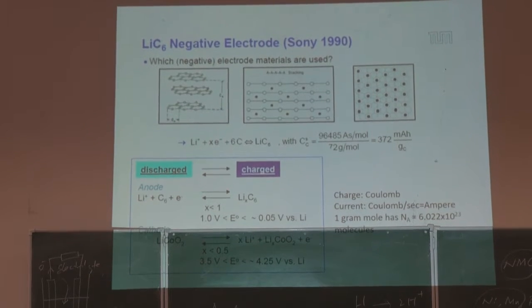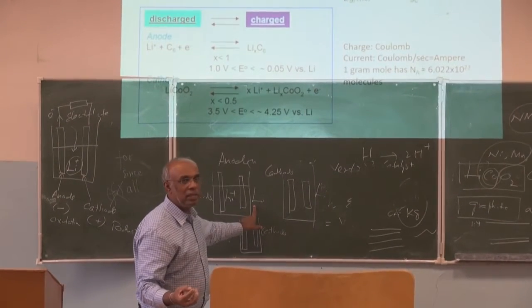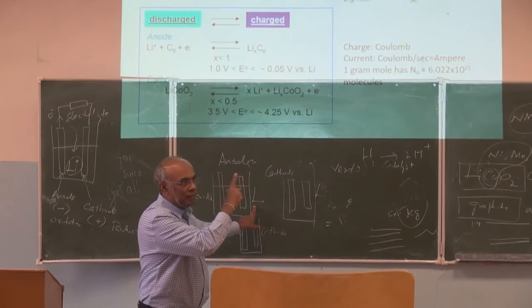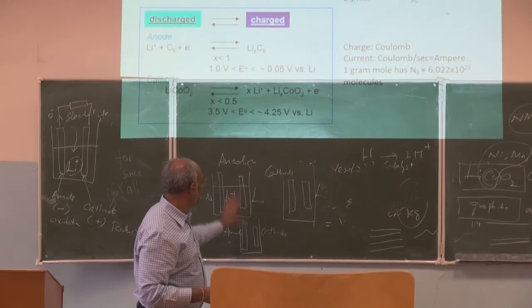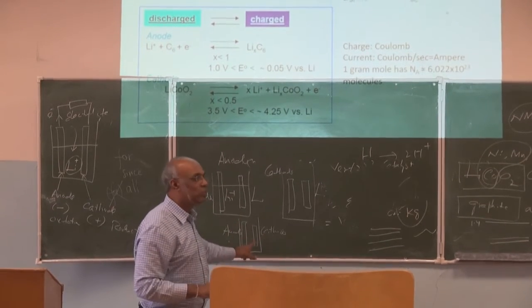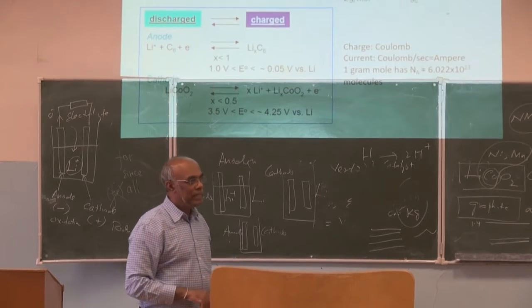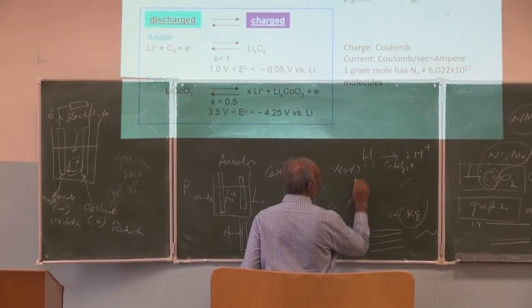So that's why one electrode here is fine. We have lithium, an infinite supply of lithium. But when you put the two materials together, that's the real battery, this one, right? This is how you screen your material. Suppose you give me some material, if I want to use it as an anode, the first thing I do is test with lithium. That's the half cell. Then if I want to test in a full cell, I have to use it this way, but in that case you need to have one electrode already pre-lithiated. They call it pre-lithiation.